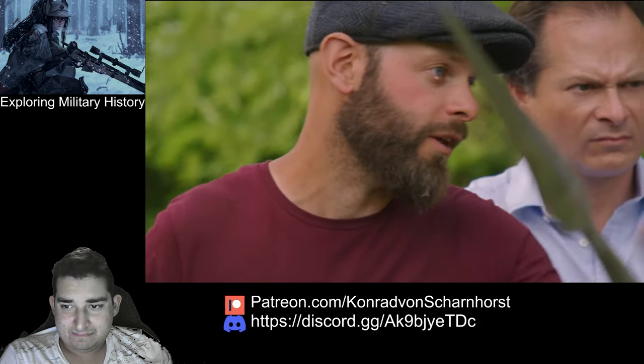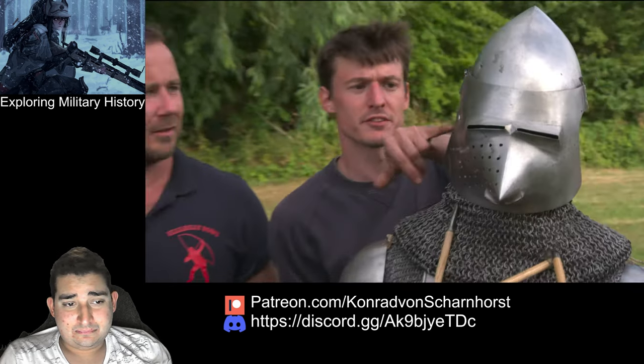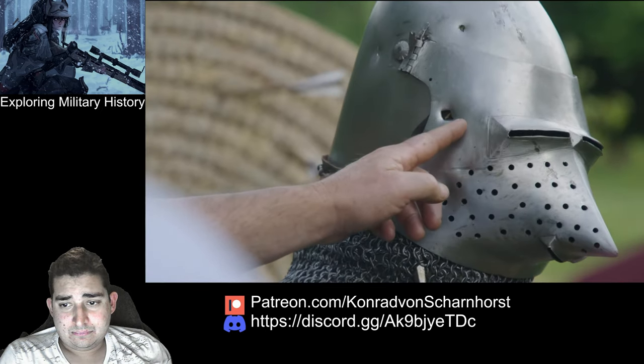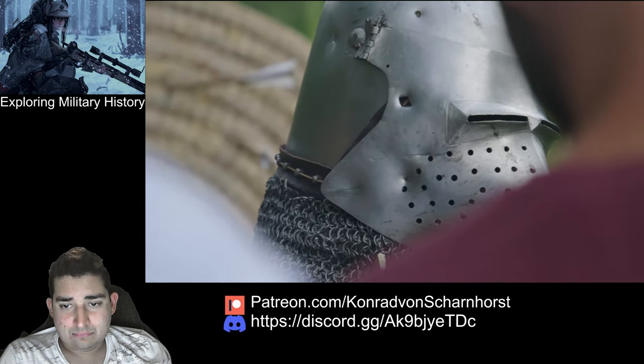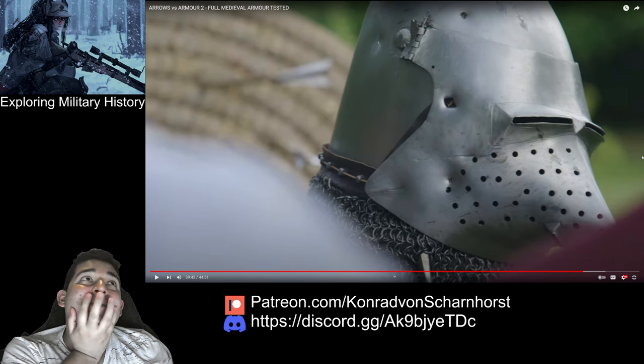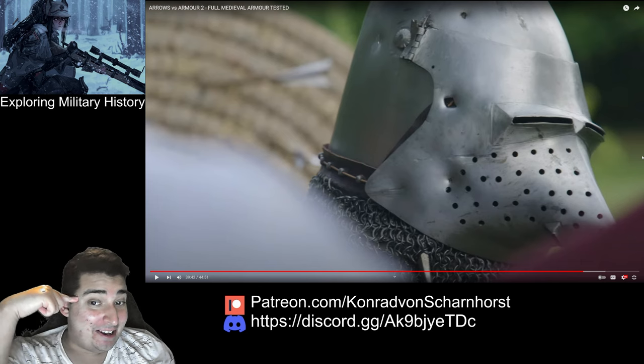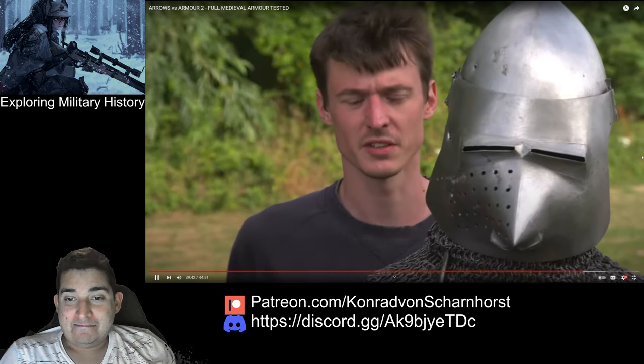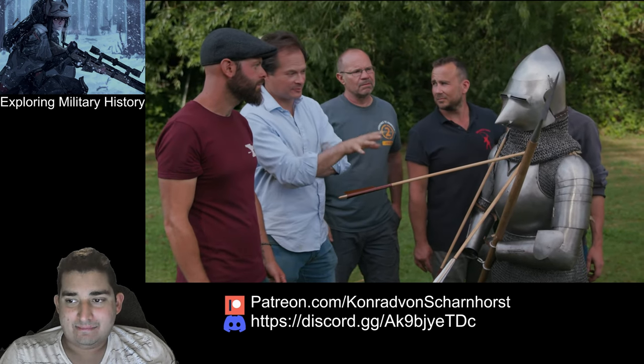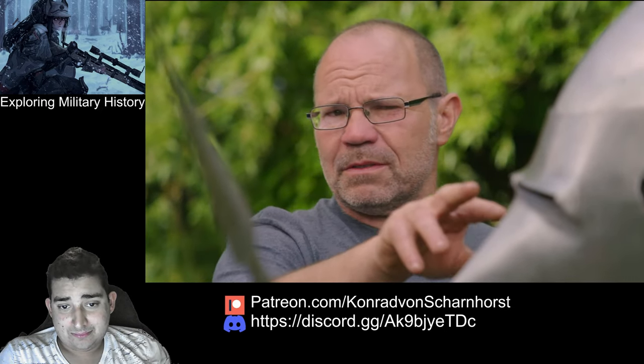Look at that hole — that's the first thing I want to talk about. An unhardened head has done some damage there. This is the thinnest part of the visor — probably about 1.2 to 1.3 millimeters — and not only is it a big hole into the helmet, it has steel behind it. Had that been 15 centimeters over, that's in the face. If the visor was a little more forward and that went in, it's going into your eye socket — and you're dead.